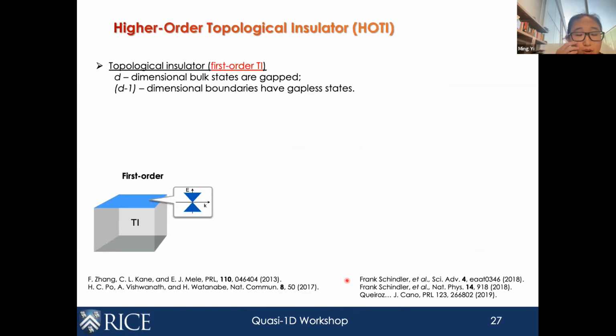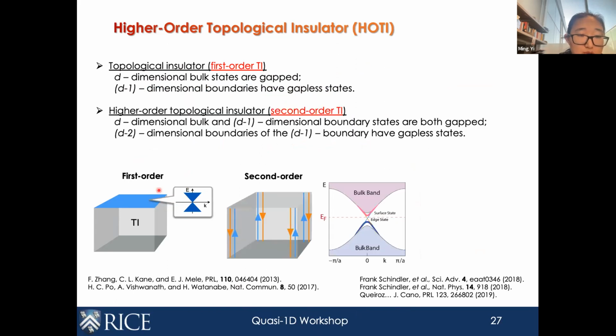But with this kind of building block, one can think about realizing higher order TIs, which I don't think I need to introduce again, since Fan has already very nicely demonstrated. But beyond the first order TI, if one finds a way to gap out the topological surface states of a 3D crystal, one can have a situation where we realize hinge states living in a gapped surface state, living in the gapped bulk state. And this will be a second order TI. And then furthermore, if we find a way to gap the hinge states, then we can get to the third order TI where we have corner modes.